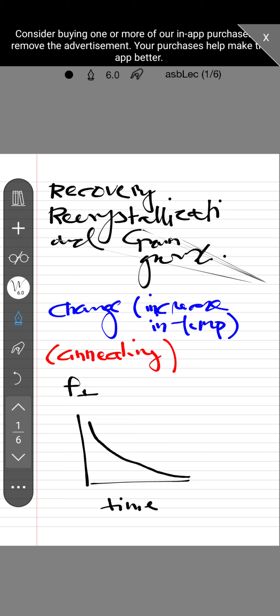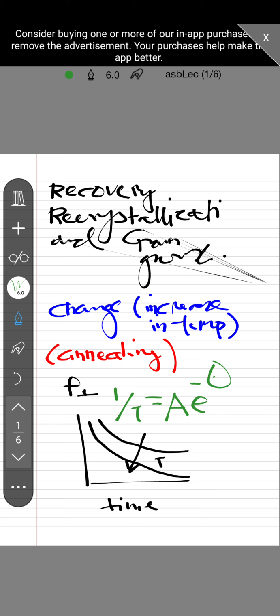and the rate is faster if we increase the temperature. So temperature is in this direction, so there is a decrease. The lower the temperature, the more time it will take to ease off the stress and to decrease the dislocation density. This is an Arrhenius type of equation, and we can represent this nature by the formulation 1 by tau, which represents the time, equals A exponential of minus activation energy Q by RT.